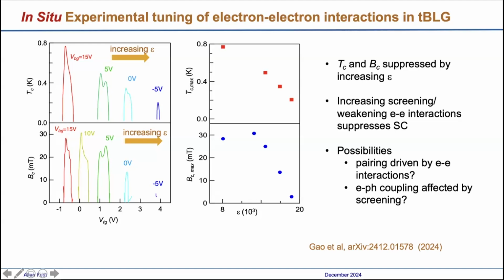Of course, I would love to say that this means the pairing is driven by electronic interactions rather than phonons. We probably cannot reach that conclusion yet, because electron-phonon coupling can also be affected by screening. But what it does say is that electronic interactions are important, maybe in addition to phonons, with screening or something facilitating it. Okay, waiting for theorists to chime in.